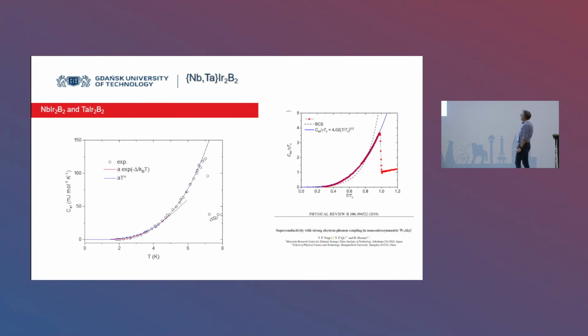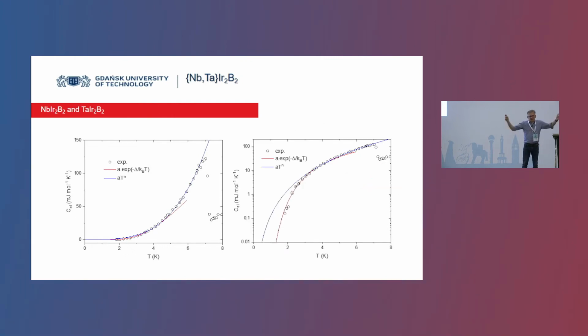proposed by the authors. And I thought maybe that's what it should be. But the same data, the same fits, the blue one and the red one. And what I will do, I will change the linear scale to logarithmic scale. And big surprise, the power law doesn't work. Not at all. But you cannot see it when you plot it on a linear scale. So you have to be very careful if you see that the power law fit of the heat capacity works for your compound. It's good to plot it in logarithmic scale.